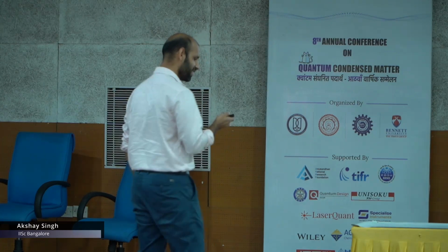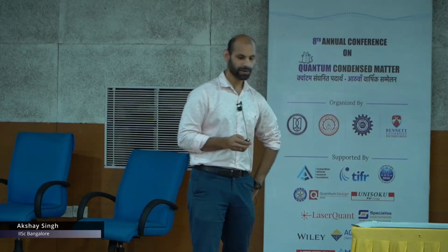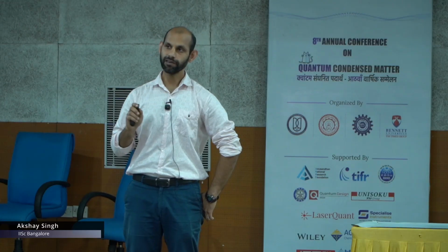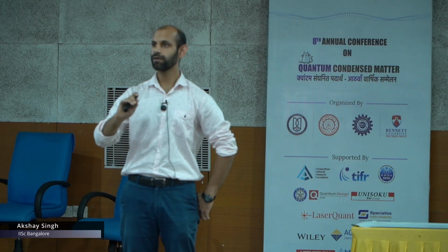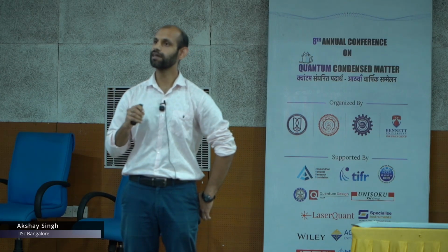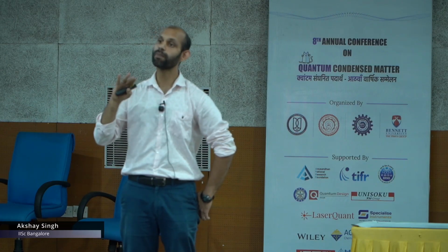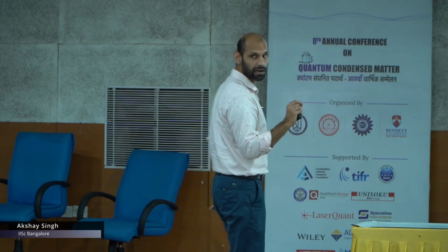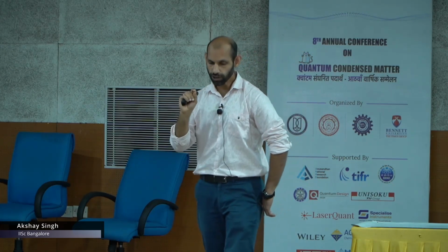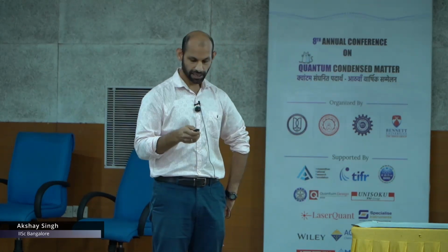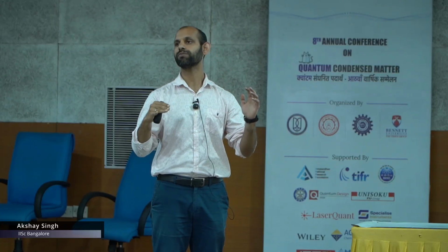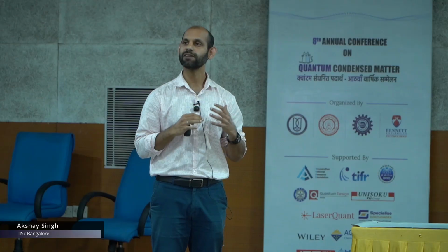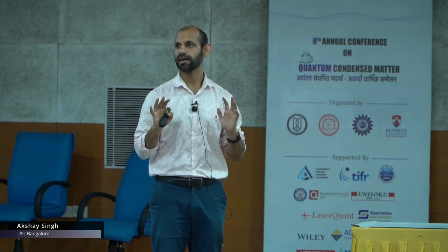Great question. Of course, when people think about biexcitons, they want to see power law dependence. But firstly, in pump probe, you don't see power law dependence because the signal is already nonlinear, so it scales linearly with pump and probe power. So you can't do pump probe power dependence for the biexciton. However, you can do PL, photoluminescence, for the biexciton. What complicates our system, we feel, is this inherent relaxation process to the interlayer exciton. So we are not sure that we will see power law dependence in that biexciton.